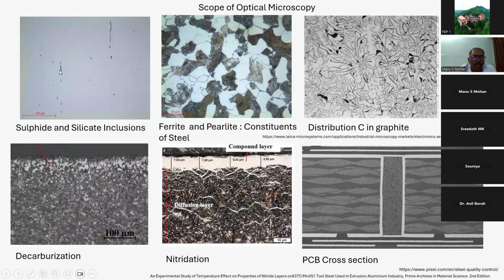There is no need to go to scanning electron microscopy or transmission electron microscopy. In fact, very rarely, when they want to ascertain the composition, they go for EDS. Otherwise, they don't even go for EDS. By morphology, one can check whether it is a sulfide or alumina or oxide or silicate. So A type, B type, C type, D type, they say in the industry, all by morphology.